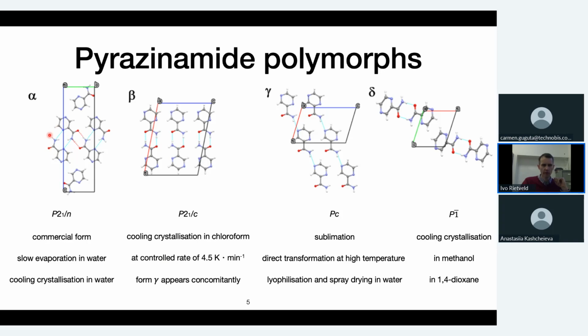Alpha is, say, a combination of 4 molecules bound with hydrogen bonding. In beta and also delta, we see the dimers appearing, whereas gamma actually is a little bit stranger in the way it is crystallized, because here the molecules are turned and you see, in fact, chains running through the crystal structure. So alpha is mainly the commercial form that you would find. If you cannot get it by commercial way, or if you would like to have better crystals, generally slow evaporation in water or cooling crystallization in water will provide alpha crystals. Beta is the hard one to get, in fact.